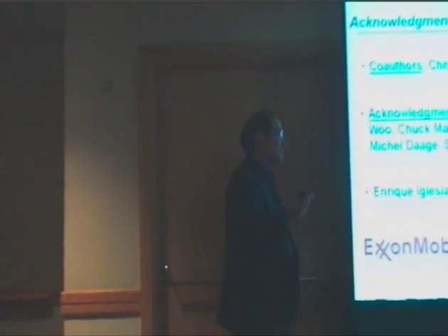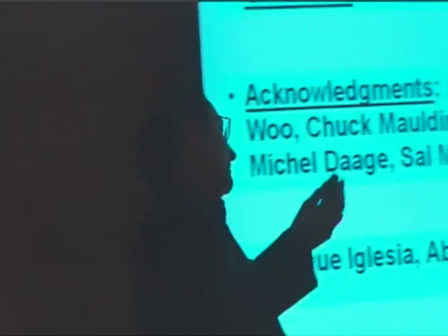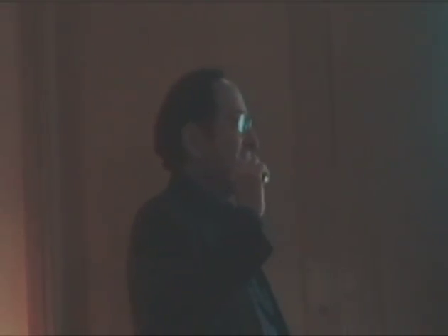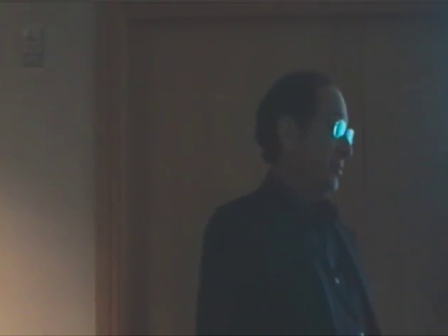Well, except for my spillover, that's the reason I mentioned that, because you can reduce the surface, it can actually become active as a catalyst in its own right due to spillover. Okay. I think my bottom line conclusion is that you can make the mixed metal oxides with any of the supports. Some are a little more prone to it. Alumina is well known to have vacancies where you can get cobalt to interact to form cobalt aluminates. Silica can do it, other ones can as well. So that's another area that needs to be worked to really make something extremely robust.